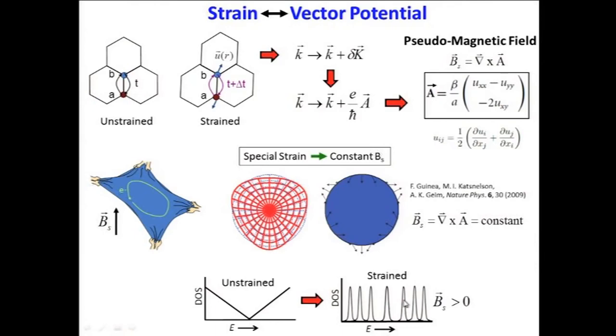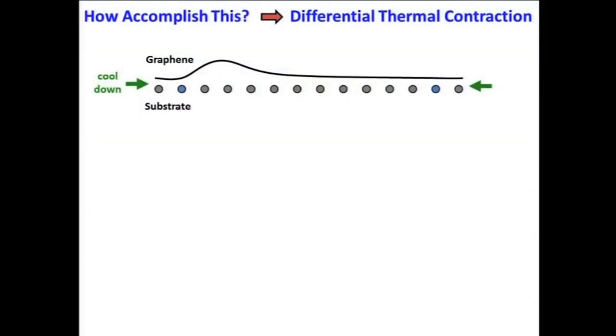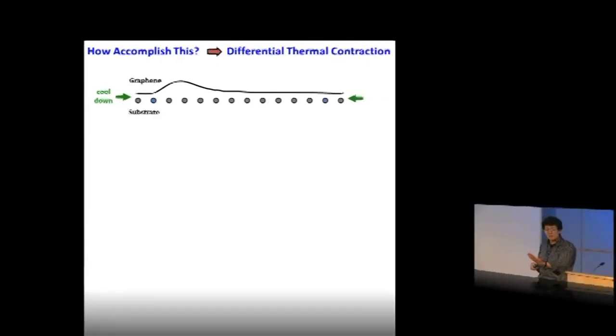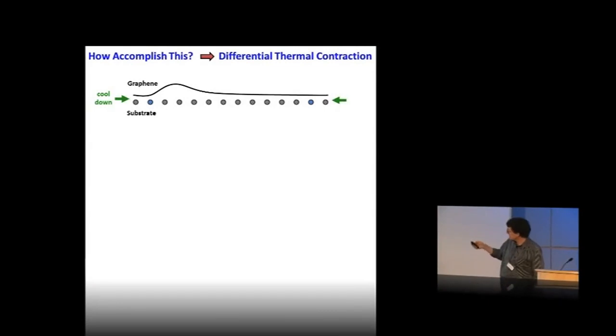And in that paper, they actually suggested an idea of using differential thermal contraction. And so that's what we did. We tested this idea by using differential thermal contraction. The idea here is that if you put graphene on a substrate and then cool it down, graphene does not shrink that much, whereas other materials will shrink more, and that can lead to a large buildup of strain in the graphene, which could then provide possibly highly strained regions which might show some of these effects. That was an idea that they mentioned in their paper.